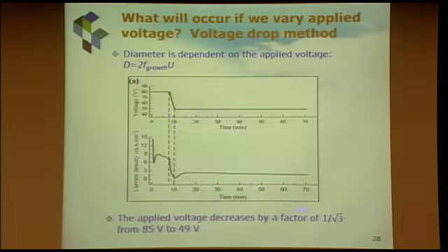There is this square root relation. So actually the key is you cannot just look at this linear relationship when changing the voltage. You have to look at the square root relation. So to make the pores split or merge, you need to decrease or increase your voltage by a square root relationship. This can be square root 3, 2, 4, and so on.